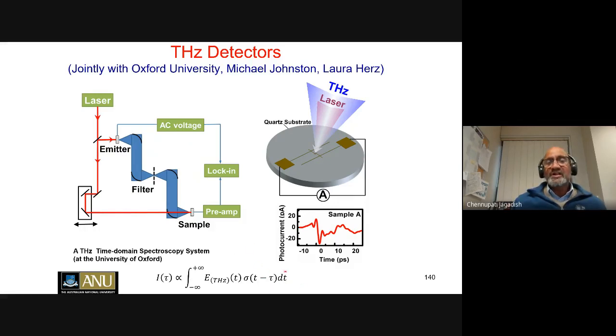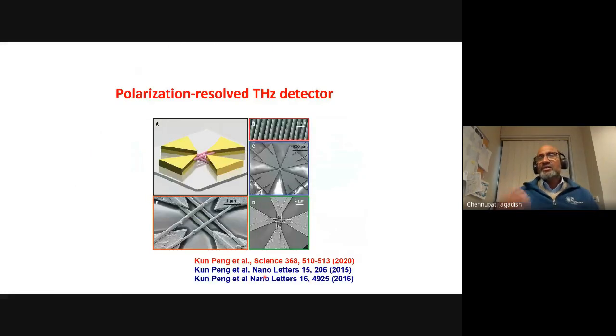In fact, initially we started using this terahertz technology to measure, in a non-contact way, the conductivity and mobility of the carriers in these nanowires. And that's where we got this idea: instead of using ensembles of nanowires, can we use a single nanowire and make terahertz detectors? To cut the long story short, during her PhD, Kun Peng demonstrated gallium arsenide nanowire terahertz detectors and indium phosphide nanowire terahertz detectors, and she's shown that the antennas which are used play an important role. She's been using bowtie antennas to create these broad bandwidth, amplitude and phase sensitive, room temperature operating terahertz detectors.